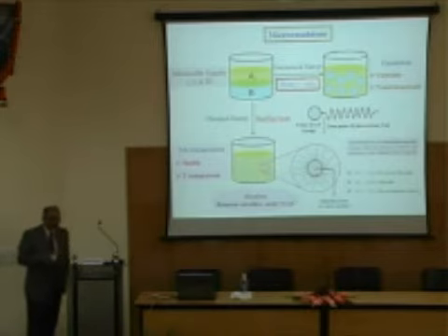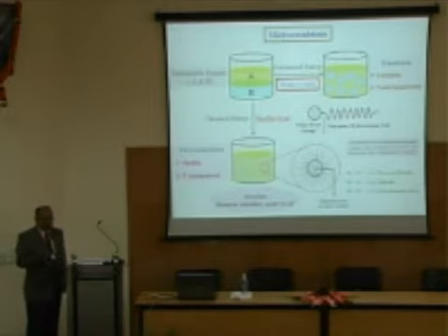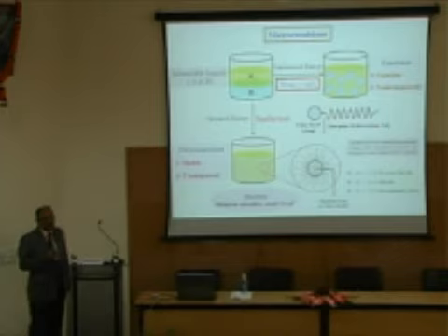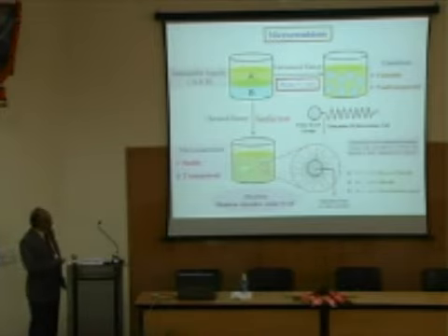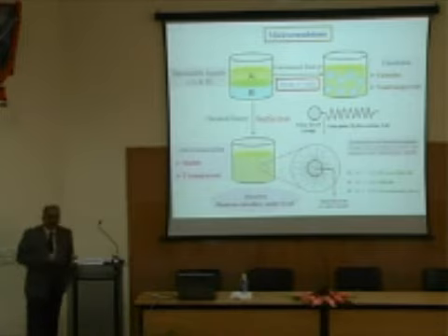After that, if you do reactions, then the molecules or particles which form will take the shape of the template which you have generated in solution. So microemulsions basically give you a template to prepare particles of designated shape and size, if you can control the size. The size normally is in the nanometer dimension, and hence you get nanoparticles.